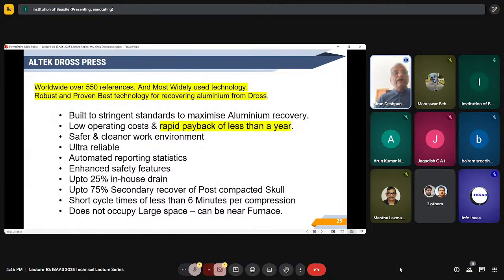So worldwide, there are over 550 references, and it is the most widely used technology of ALTEK. It is a robust and proven best technology for recovering aluminum from the DROSS. It is built to stringent standards, UK and German standards, to maximize aluminum recovery. The pans do not deform. The DROSS press works for at least 10 years without any deformation of the pans. It has the lowest operating cost and a rapid payback of less than 1 year. Within 1 year, you recover your money.